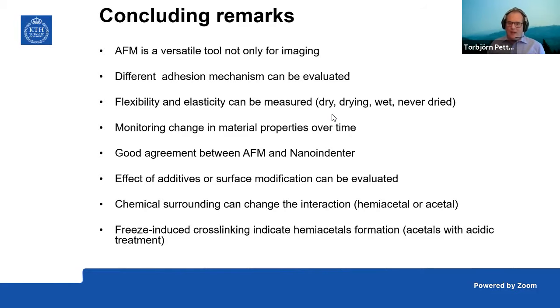The effect of additives or surface modification can be evaluated with AFM. Chemical surroundings can change the interaction, like in the hemiacetal or acetal case. And for the aldehyde cellulose, freeze-induced cross-linking indicates hemiacetal formation, and acetal formation with acid treatment.